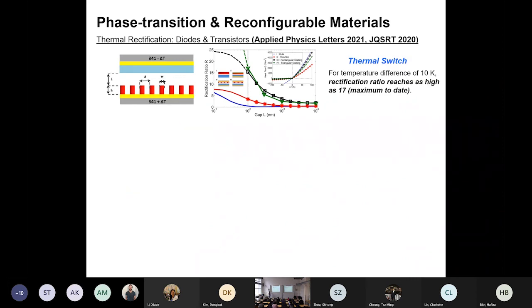So we made it. We have two structures, and by taking the near field thermal radiation, we could obtain a really high thermal radiation at the nanoscale gap, the 100 nanometer gap. And the bottom surface here, as you can see, the red color, the surface gradient structure is VO2, vanadium dioxide, the phase change material. I use it, and the yellow one is just gold. On top, the light blue is BN, boron nitride. So nothing new, these are still materials that should be used.